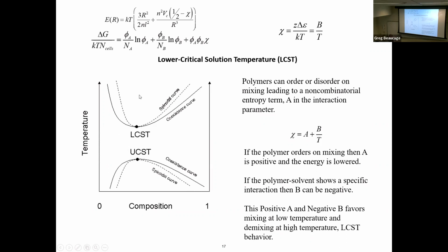Anyway, this is a normal phase separation for polymers, like heating it, it phase separates. Later on, we'll look at poly(N-isopropylacrylamide), PNIPAM, which people use to make drug delivery systems. You can make a gel out of PNIPAM and load it with drugs. And then when it reaches a certain temperature, like cancer is a higher temperature than the normal body, you can tune it to collapse at that temperature when it heats up by this lower critical solution temperature, and then it'll dump its load there. A lot of drug delivery is centered on PNIPAM and loading it with things. We'll see a paper in here that uses that.